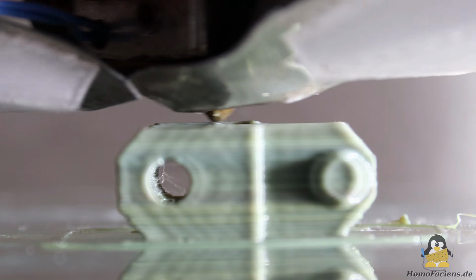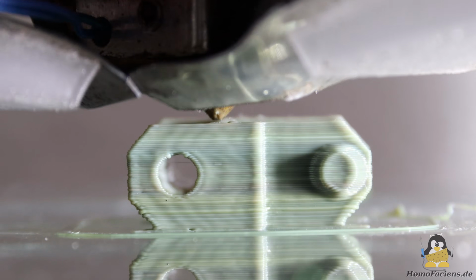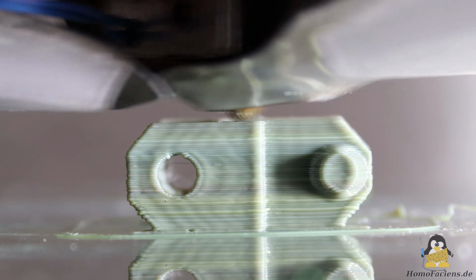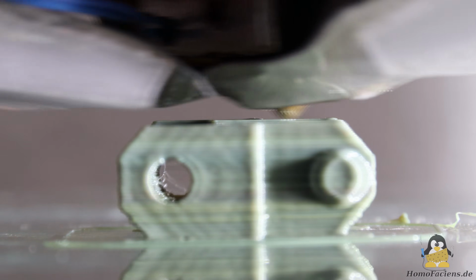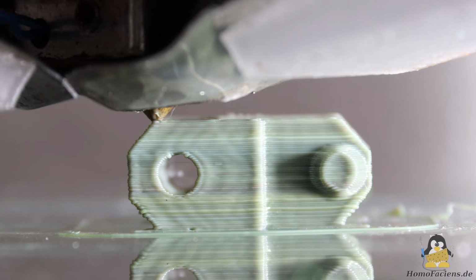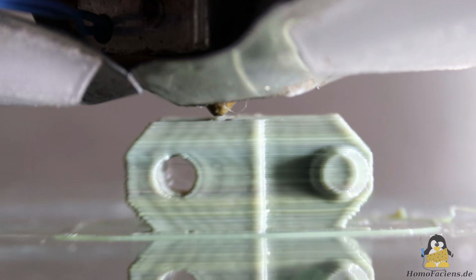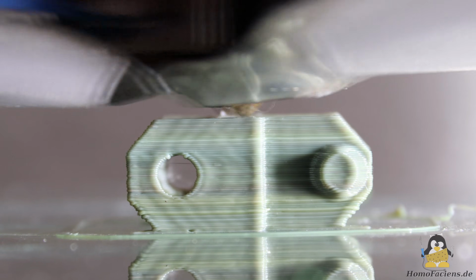Let's move on to the recycled PLA I produced myself. The printing temperature is set to 215 degrees Celsius, a 0.5mm nozzle is installed, the layer height is set to 0.2mm and the extrusion width is 0.5mm. The print speed is set to 30mm per second with an acceleration of 500mm per square second for the outer walls. I have demonstrated this test print using recycled PLA several times. The printed object clearly demonstrates, via straight walls and edges, how uniformly the material is extruded. The result is good, though some layers protrude slightly, indicating minor fluctuations in extrusion.